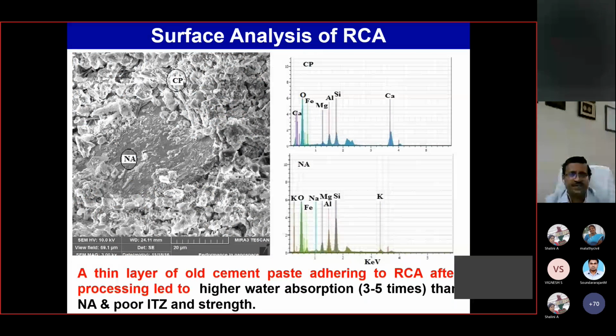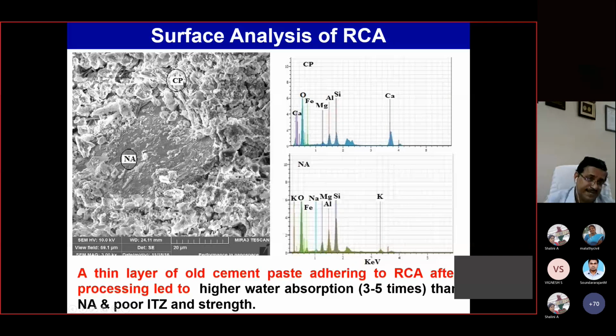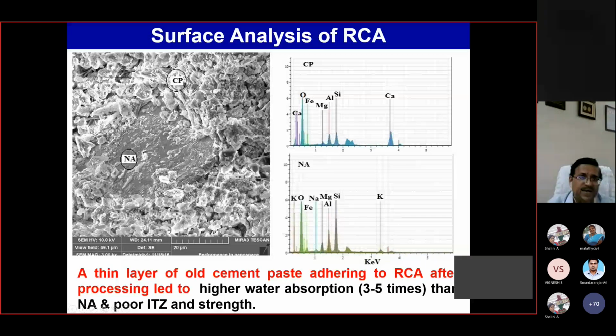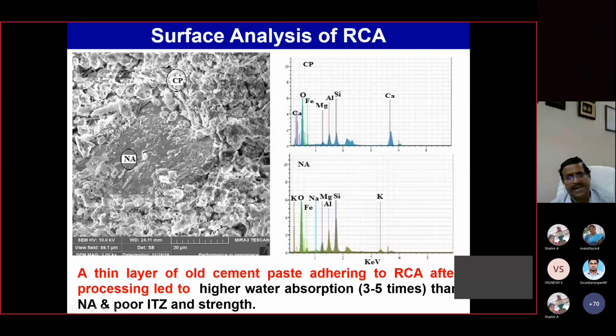What I have said is that you have to understand what the problem is, why people are not using this recycled concrete aggregate. This is the problem. If you take the same analysis of your recycled concrete aggregate, this is the aggregate that was used at that time, from where the demolition was achieved, and this is old cement paste. These adhered mortar and adhered cement paste are honeycombed. So this cement paste is the weakest zone.